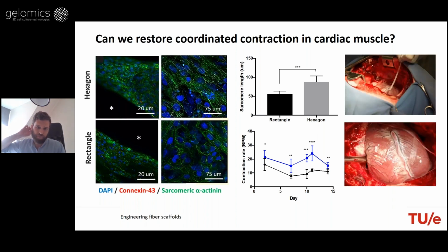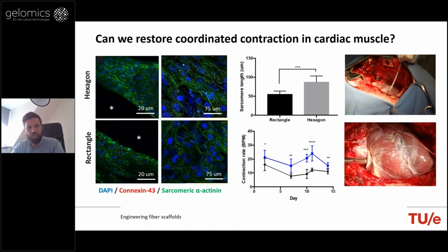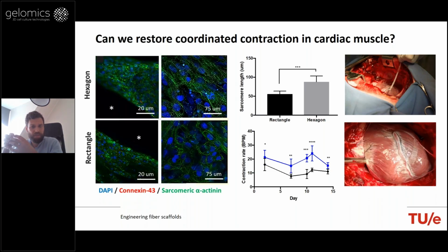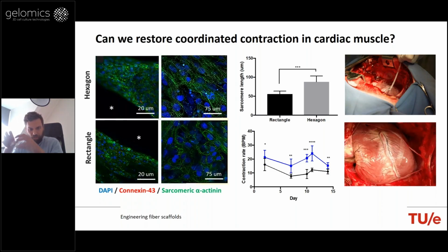We went one step further and investigated, given these elastic properties of the constructs, whether we could explore the use of these constructs towards a minimally invasive delivery. So basically what we did was to roll these constructs and deliver them through a small catheter. These are the images that you see here, delivered in a beating pig heart. As you can observe, the entire scaffold, when in contact with the wet layer of the heart, was fully unfolded, and it was in place for the time that we did this test, which was just 3 days, and cells were alive. So the scaffold showed shape recovery properties. It was able to unfold and then somehow align.